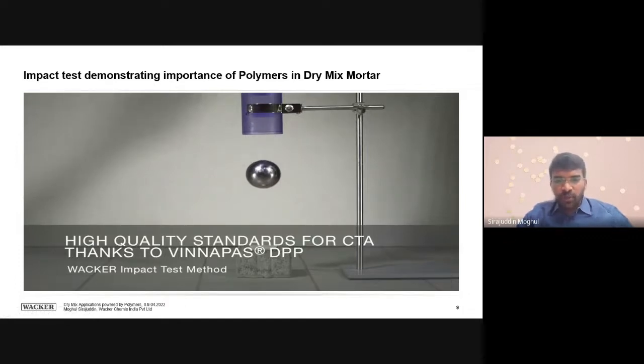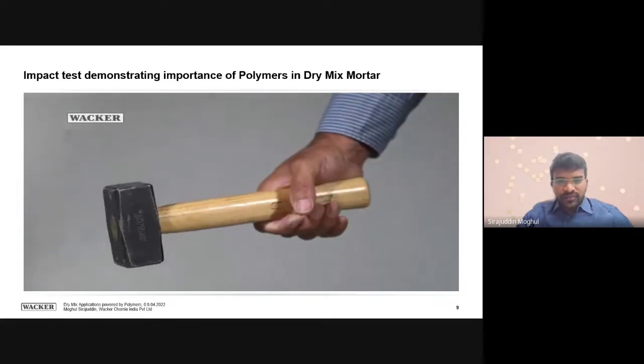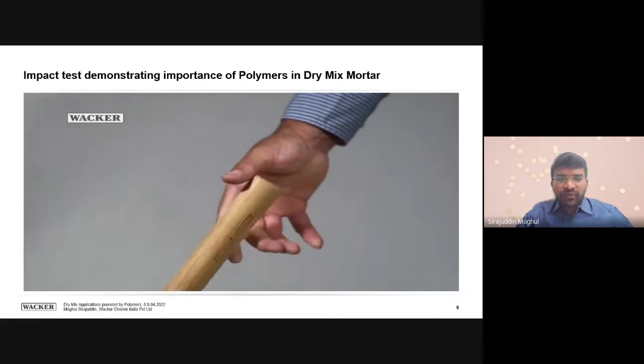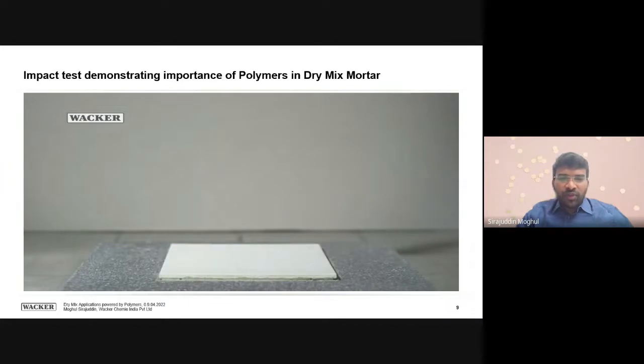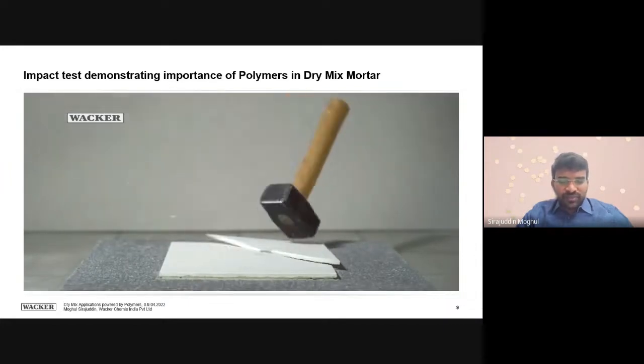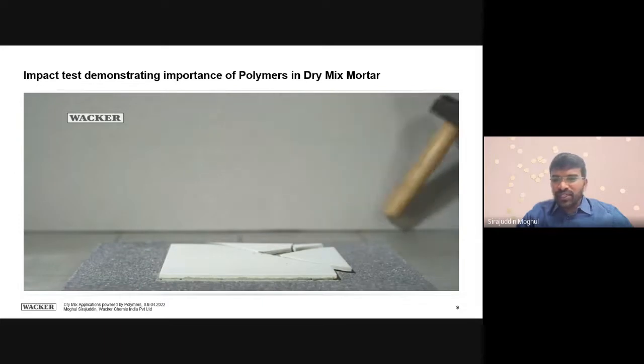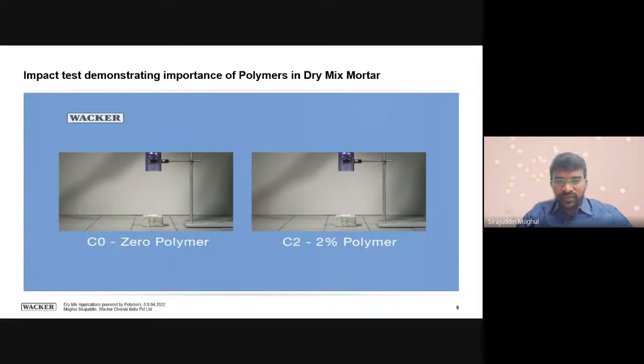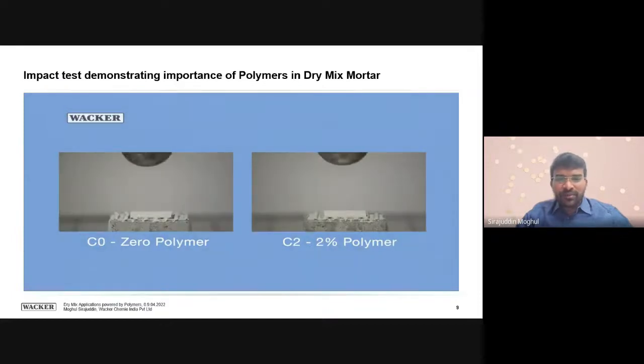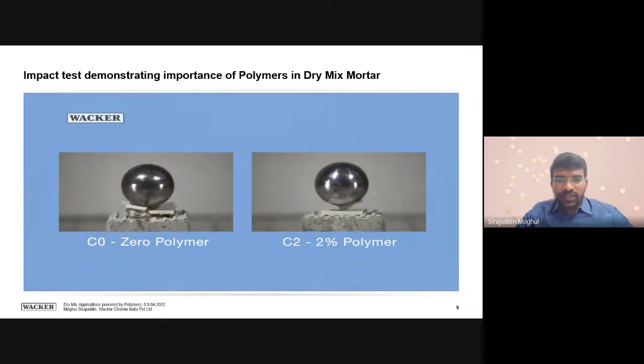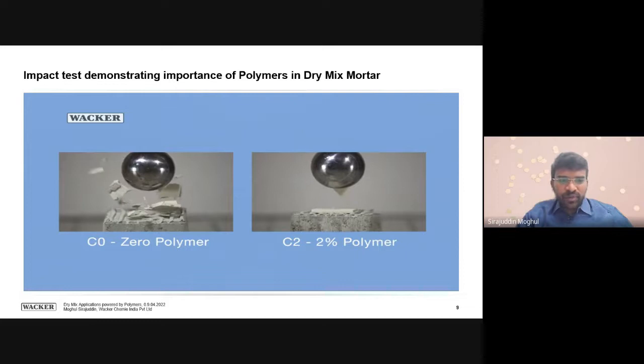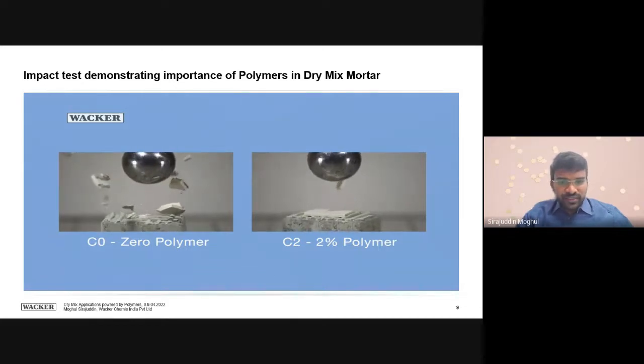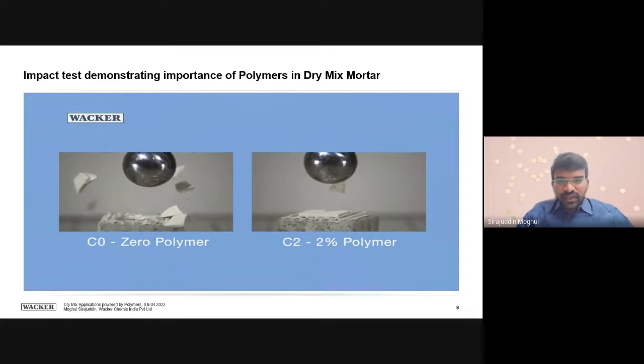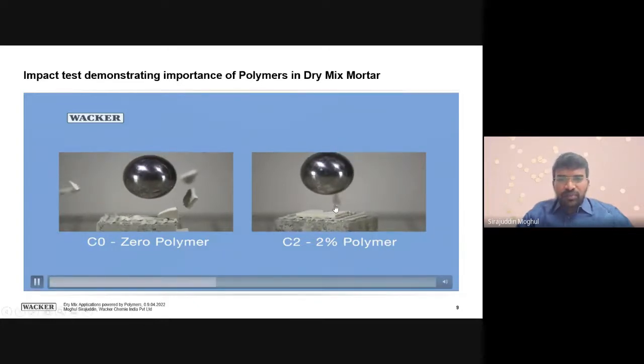So here is a ball of very heavy weight, which is falling on the tile. And you would have seen in homes, whenever we have tile flooring, when a heavy object falls on the tile, it breaks. And people feel that since a heavy material has fallen on the tile, and tile is a ceramic material, it will obviously break. But it is not because it's a brittle material, it is because we haven't applied it properly. See, if it is without any polymer modification, you can see the tile has shattered. And if it is polymer modified to a certain extent, it is intact, but only a certain part of it has broken.